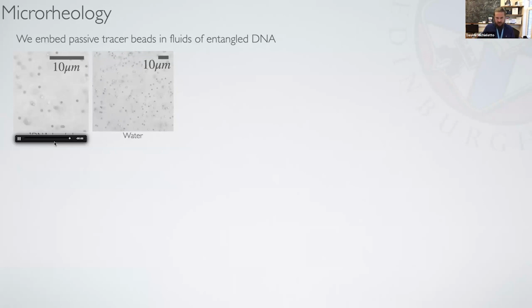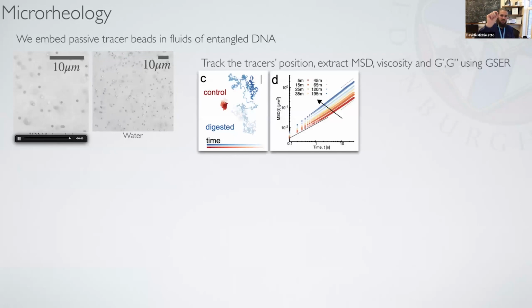Essentially, you just monitor the particles. And so what we do, we track the position of the particles with an algorithm. So in this case, for instance, I was cutting DNA, so the control, the full length DNA. If I have a particle in a very long solution of DNA, this will be a very stuck particle, so it will not move a lot. Once it is digested and the DNA is being cut, the particle moves a lot within the same time window.